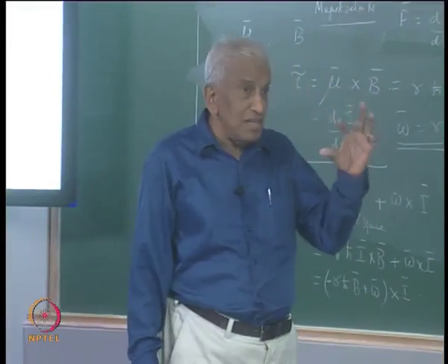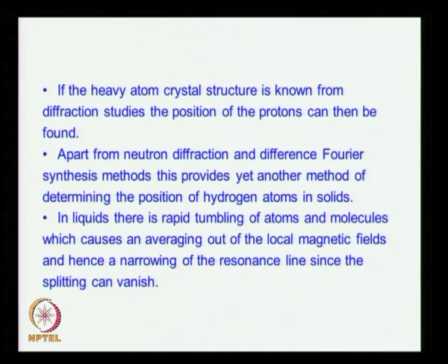So, one can measure the length and orientation of the interproton vector from this angular variation, and this, when coupled with additional crystallographic information from structural data, one can even locate the positions of the protons. This is, as we already discussed, a rather difficult problem.